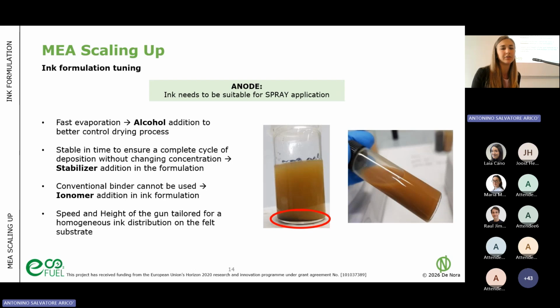As I said, in the case of the anode deposition, we are using the spray coating technique. So, of course, we have as a substrate, in this case, a nickel felt from Bekaert. And since we are spraying the catalyst on top of the felt, we need the evaporation to be fast. Otherwise, the substrate is going to be completely wet. So in this case, we needed to pass to a hydroalcoholic solution, not just a water-based solution.